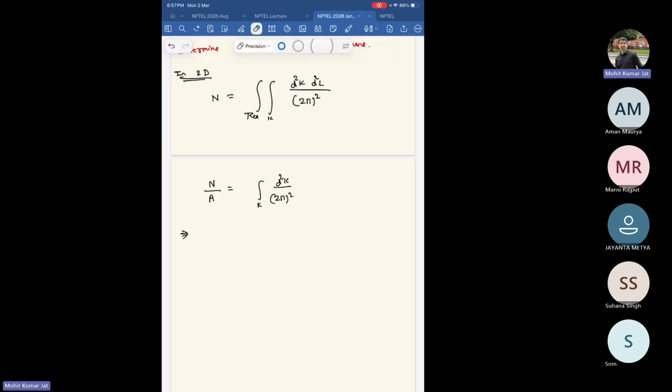and divided by area is nothing but carrier density, and there will be a factor of 4 also, which you can write as 4 equals 2 times 2. 2 is because of the spin of the electron, and 2 because of the valley which we discussed in this class, k and k prime. They are inequivalent points, so they will also come here.